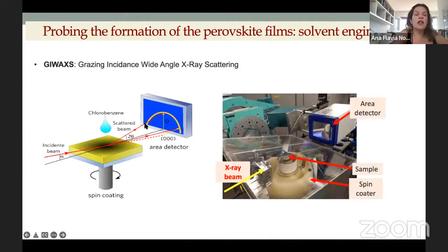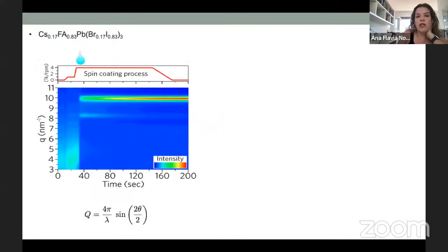So we managed at that time to bring our spin coater from our lab in Campinas, and we set the spin coater, as you can see, in a beamline. Okay. The X-ray comes this way here. It is our area detector. Also, we built this chamber around the spin coater, where we are able to control the atmosphere inside, and also the time to inject the antisolvent. Also, this work was made by Rodrigo. So we use this kind of perovskite here with cesium and formamidinium, and also with mixed halides.